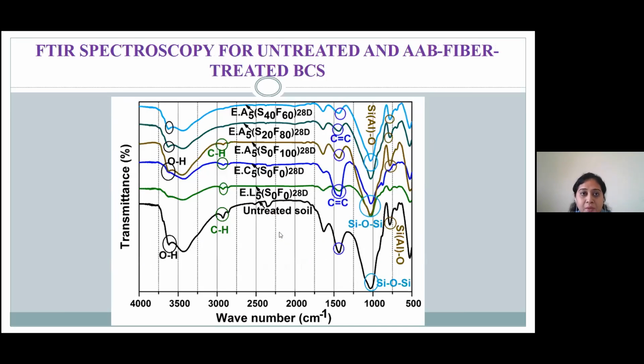Coming to FTIR spectroscopy, that is Fourier transform infrared spectroscopy, it is used to characterize the various molecular bonds. We used a JASCO FTIR setup with the potassium bromide pellet arrangement. The transmittance spectral range was maintained from 4,000 to around 500 per centimeter for all the samples.